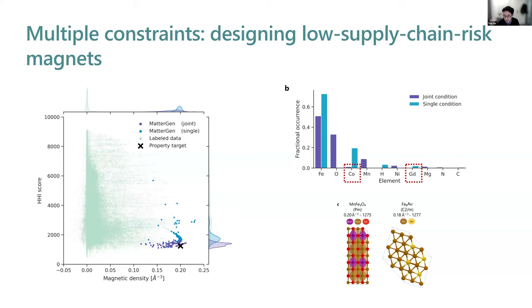And we have found that by optimizing these two properties, we can actually bias the generated distribution towards the lower end of the HHI score. And if you plot the distribution of elements, you can see that we're getting rid of the elements with a higher supply chain risk compared with other elements. And we are generating a lot of materials that are mostly composed of iron, because it's one of the lowest supply chain risk elements. And this is one of our initial demonstrations of the model in a more realistic materials design problem. Obviously, this is pretty early stage.